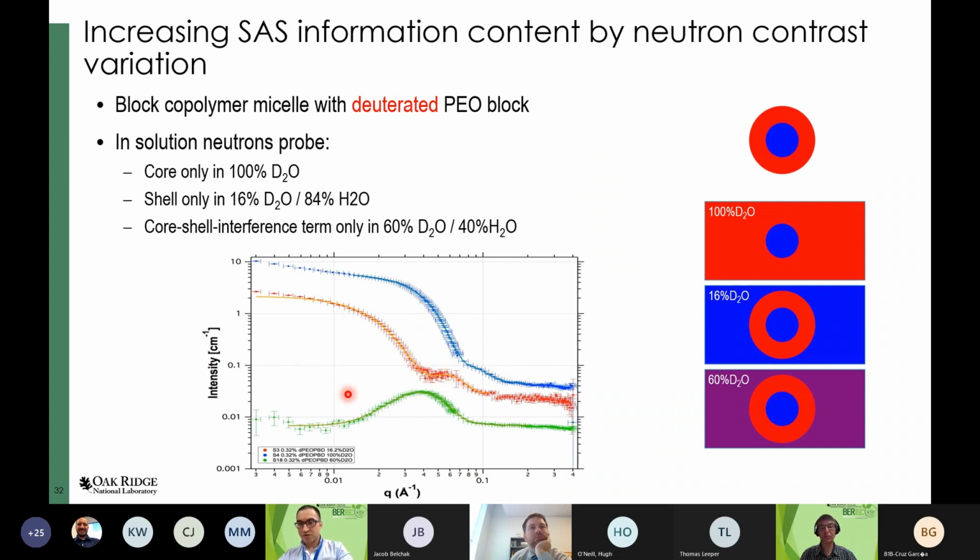So you would spread all of this out, you would smear all of this out, depending on how much of a distribution you have. Basically, if you have a distribution of particles, the intensity all adds up, so you get it all smeared out, broadened out. So it will interfere. How much depends on the case. But you can introduce what we call polydispersity into a model like this if you have that kind of effect.